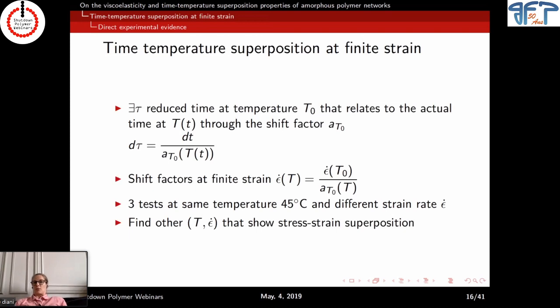So now, since we want to deal with shape memory properties, it's not only small infinitesimal strain, sometimes we have large transformation or large deformation. We wondered, okay, all those shift factors that are very useful for us because they make the link between the temperature and time, do they apply for finite strain? If it does apply, what we should get is being able to define the reduced time for any temperature, make the link between the reduced time at a given temperature T0, and the time at any temperature.